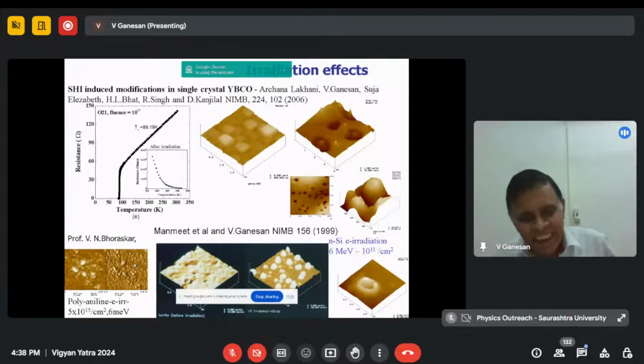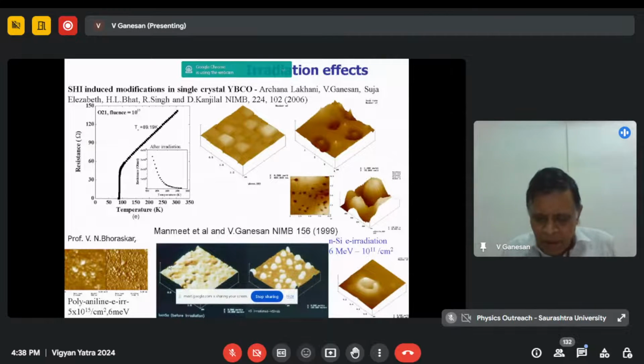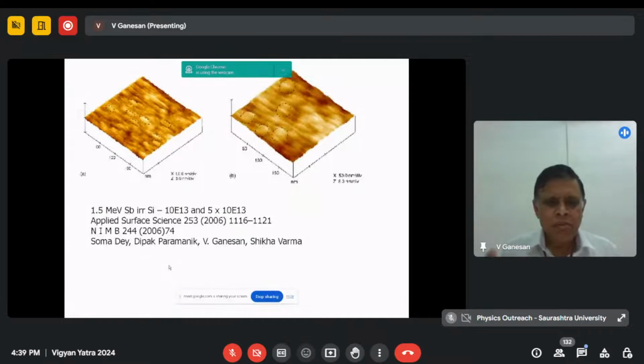But then, interestingly, we did all these experiments over a period of time. Of course, this is done with Professor Shikha Varma. She's a very known figure nowadays. She was there earlier in the Institute of Physics. I hope she's also still there. And then for them, we tried to see a small amount of blister formation at a low energy really. It's not a very high energy like 100 MeV and all. 1.5 MeV of antimony in silicon. And we did a lot of very good work on this.